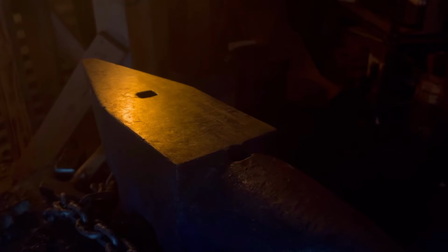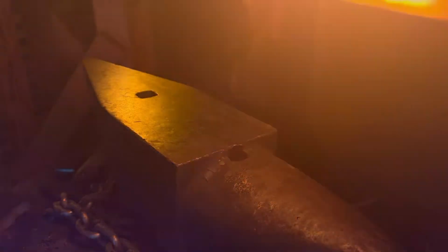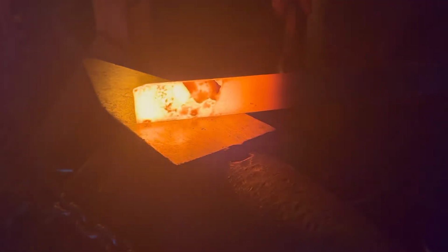If you work your steel at an improper temperature, you can cause so many problems that you won't even know are there until much later. For example, if you overheat your steel, you can start to really damage that grain structure and make it crumbly and brittle. And if you're using a coal forge, you can even burn that steel off. You'll see it in bladesmithing competitions a lot when they lose focus on a coal forge especially, and then their billet or whatever they're working on falls in half or the end falls off because it got overheated and it ended up actually burning, wrecking the steel.